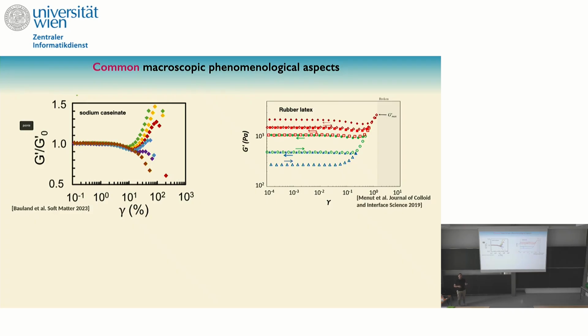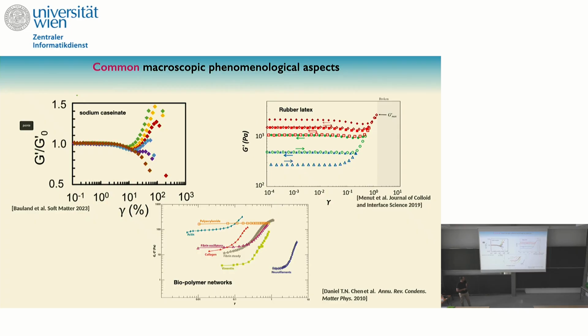And this is a very natural thing that you find in nature, because in nature, or in your body, the system doesn't want to break apart. So when you have a situation with a lot of stress, your system tries to avoid breaking and tries to resist that. For example, if you look into biopolymer networks like collagen, actin networks, and many other systems, you find basically the same phenomenology. You have a linear regime, and then you have a nonlinear strain stiffening, where the materials try to resist that deformation to avoid degradation, because degradation is not very good for your body. So there is some common macroscopic phenomenological aspect between all these materials, even though if you look at them from far away, you don't see anything in common. What is common between the cytoskeleton, casein gel, rubber, latex, and so on?